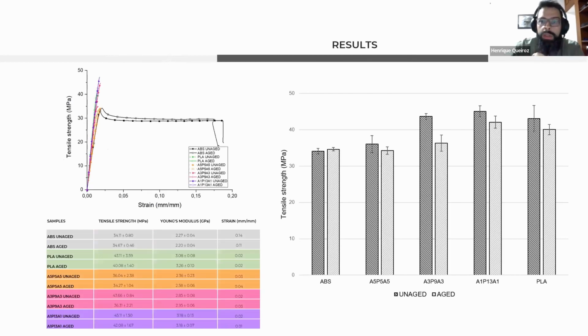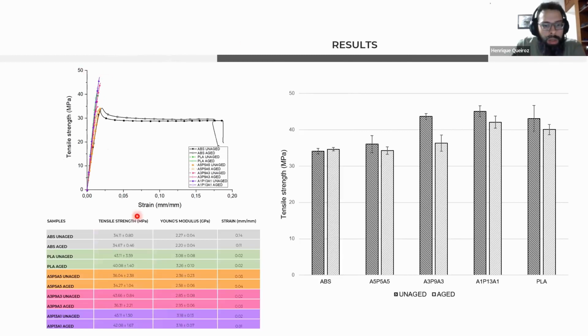So here we have our representative stress strain curves for the tensile properties. And what we can see right off the bat is that the material behavior didn't vary very much as a function of the aging. For instance, over here we have our ABS unaged, right, with the black square. And you can see it has a very classical ductile behavior. And when we look at the aged specimen, it has almost the exact same behavior and very similar tensile strength. But when we look at the PLA over here, very similar behavior both for aged and unaged, and very similar final tensile strength. And of course, a much more brittle behavior compared to ABS, which is also known.